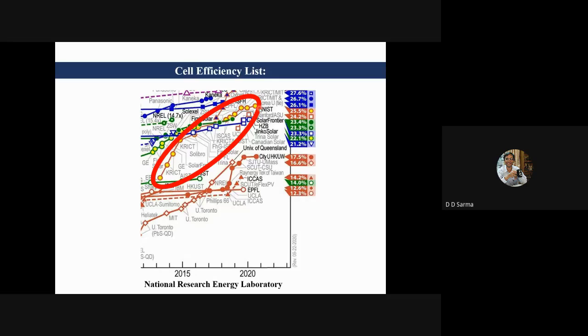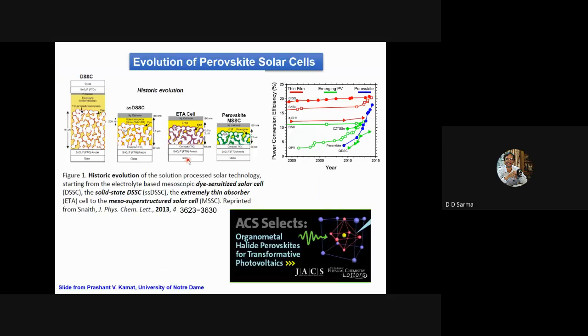The highest efficiency it has reached now is in the order of 25.5%, which is really remarkable. Not only is it such a remarkable efficiency, it also works as a very thin material. And that is very important, because if I have to make a very thick material, and all silicon technology requires